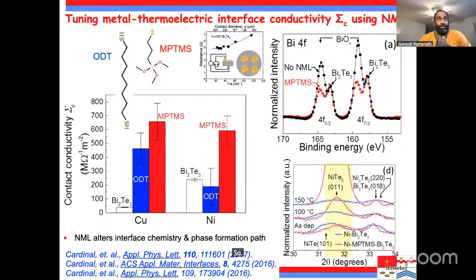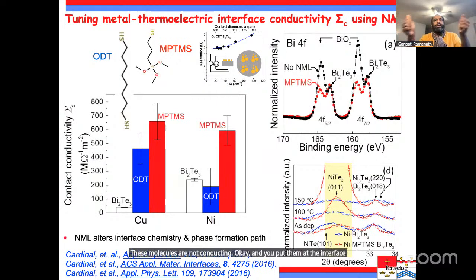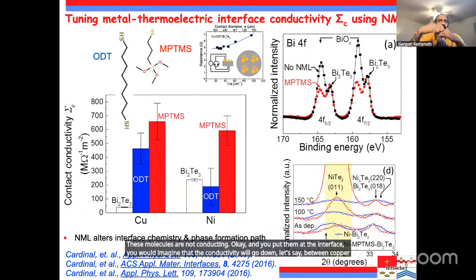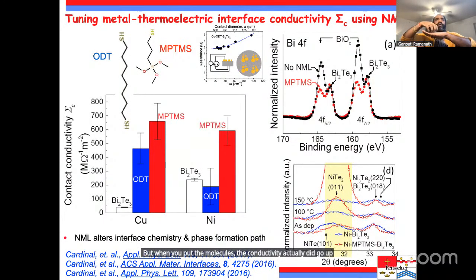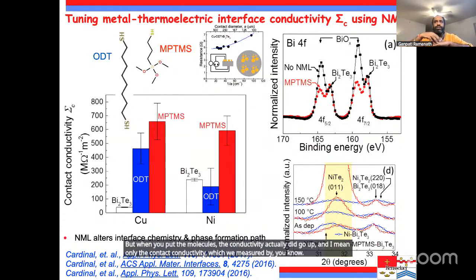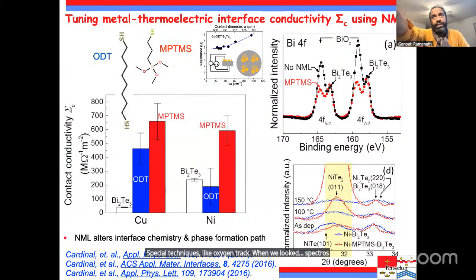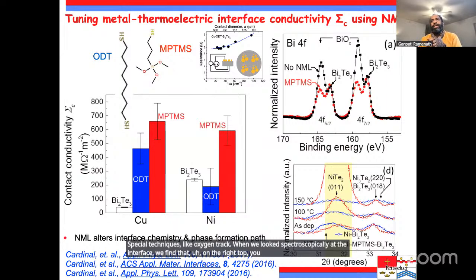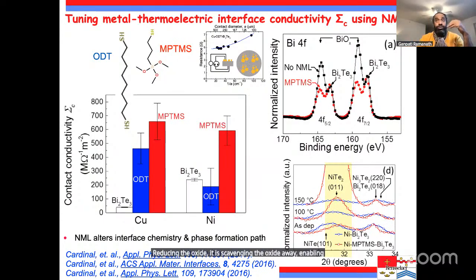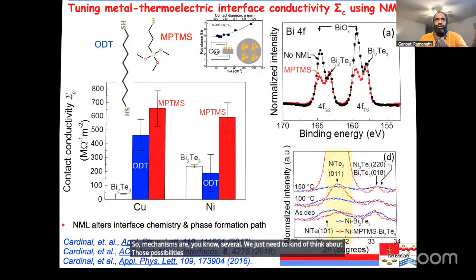So we can also use these to enhance electrical conductivity, and this again was totally non-intuitive. These molecules are not conducting, okay, and you put them at the interface, you would imagine that the conductivity will go down, let's say between copper and bismuth telluride. It's a metal semiconductor interface, okay? But when you put the molecules, the conductivity actually did go up. And I mean only the contact conductivity, which we measured by special techniques. When we looked spectroscopically at the interface, on the right top, you can see the red curve has lower peaks than the black curves. And that is because the molecular layer is reducing the oxide. It is scavenging the oxide away, enabling good conduction. So the mechanisms are several. We just need to think about those possibilities before we rule new ideas out.